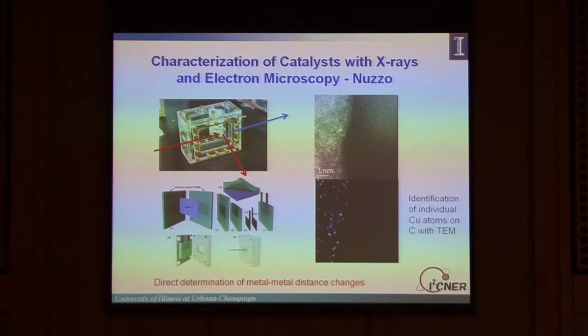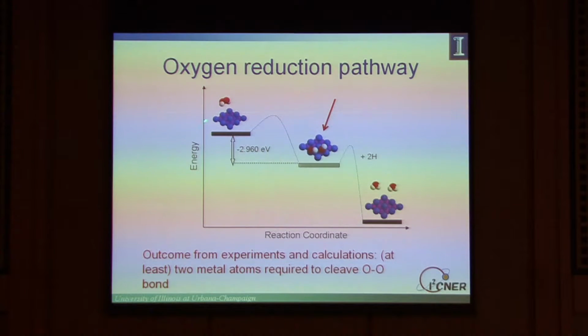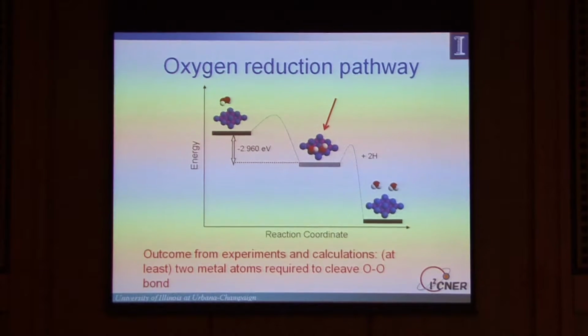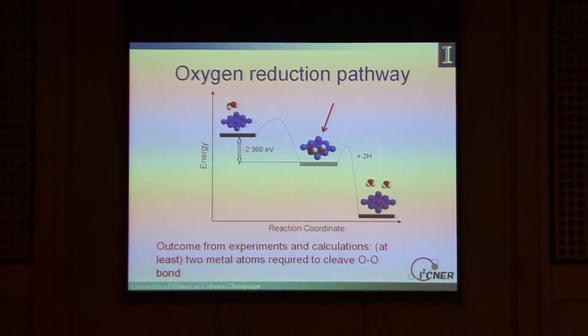All right, don't take notes. We've done X-ray scattering experiments to look at platinum-platinum distances as a function of oxygen presence and of potential. We can do TEM to look at real catalysts on surfaces. These are individual copper atoms on a carbon electrode surface. And from this, we can come up with a series of mechanistic ideas. And the outcome from all of these experiments and calculations is to show that at least 2 metal atoms are required to cleave the oxygen-oxygen bond. So that's one thing that we know we want to do.